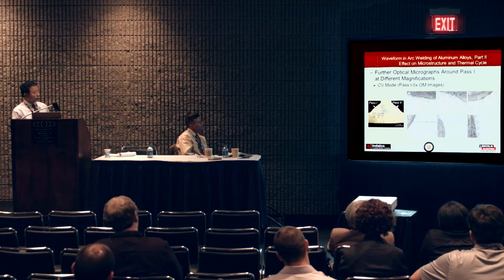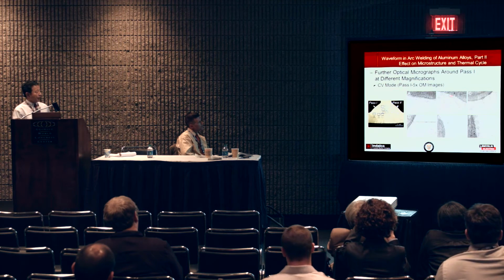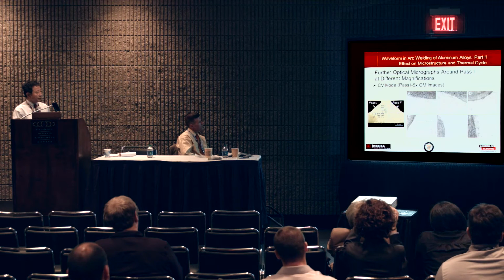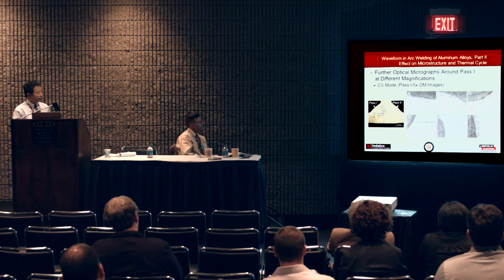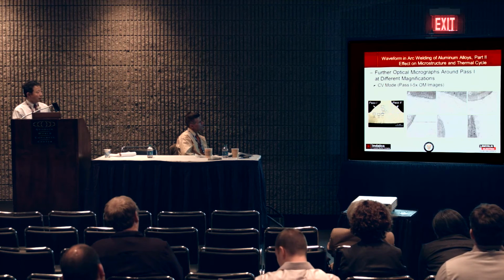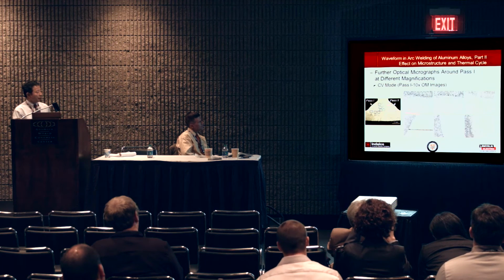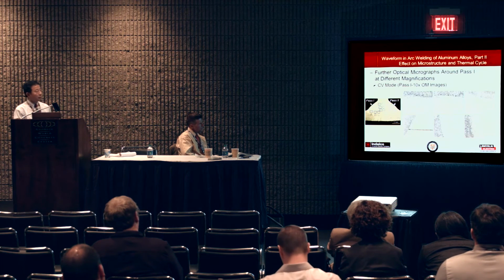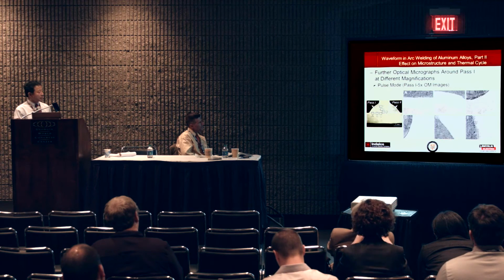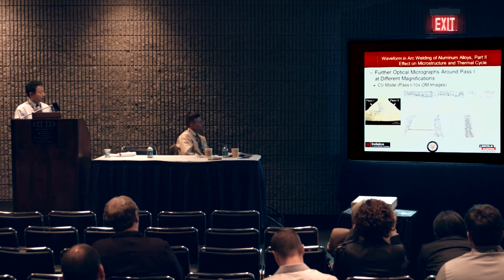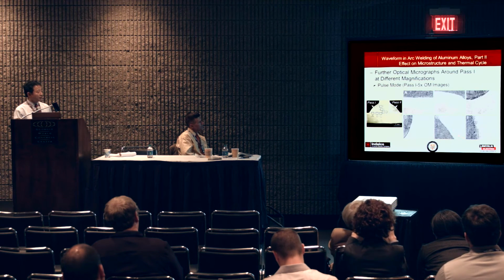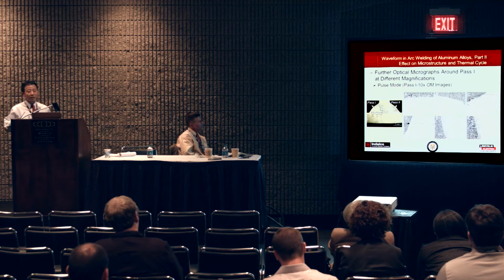And I did further, put on high magnification, compare, basically 200 microns from my fusion line, did 6-point observation with optical microscope. This is 5 times, and I did 10 times, and I found basically it repeats what I saw with low magnification. You can see that you really get pretty big grain size. This is 10 times, but pulse mode definitely gives you lots of advantage talking about grain size, grain structure.